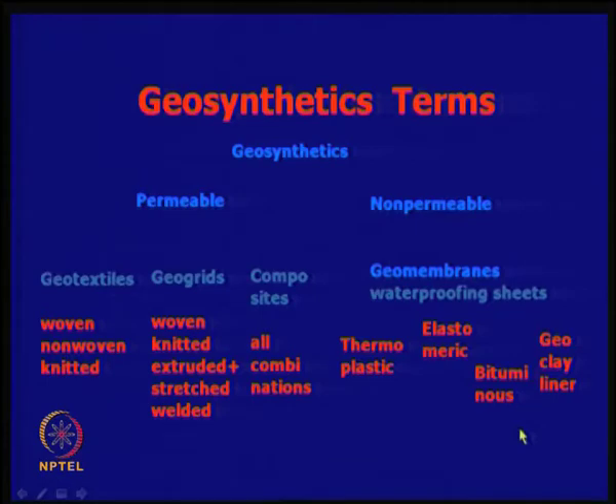We also have what is called a geosynthetic clay liner, in which you have a geotextile on either side and a bentonite powder mixture inside, and that provides reasonably low permeability compared to permeable textiles. The permeability could be in the range of 10^-2, or it could be 10^-8, or even 10^-14 centimeter per second. It could be very low here, whereas it could be very high for textiles.